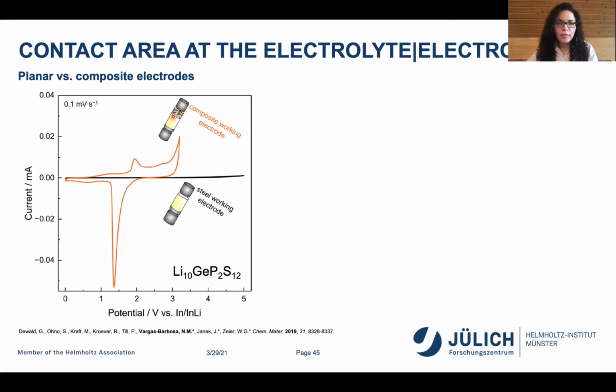So instead of measuring the pellet directly with a planar electrode, we just mix it, in this case with Super P, just conductive carbon, to increase the surface area and then run the CV. And when you do that, you observe something like this, where you now have peaks here and you seem to have some other things here. And yes, there is an effect of the effective increase of the surface area that broadens this part here.